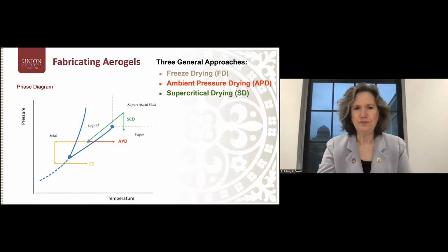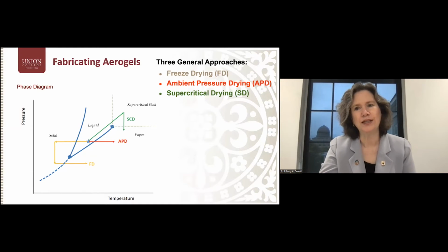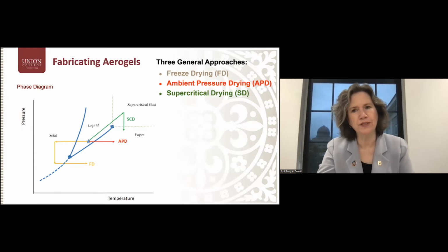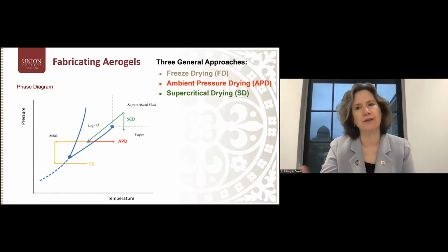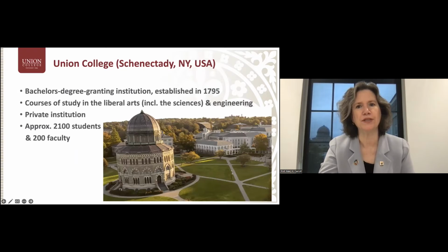And so a series of solvent exchanges, typically to go to a more non-polar liquid solvent, then in a pressure vessel to go to liquid CO2, are performed. And then in that pressure vessel, something like an autoclave, the temperature and pressure are brought above the supercritical point of CO2. And that is the method that I was most familiar with, but we did not have a critical point dryer or an autoclave that we could use for this purpose.